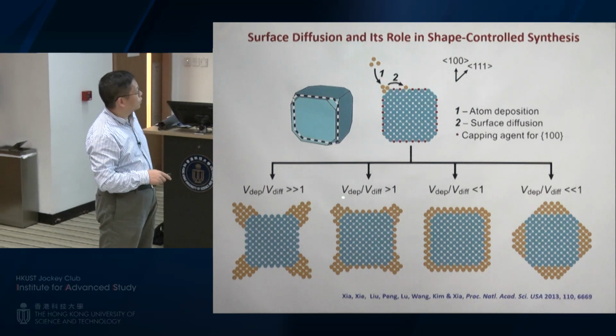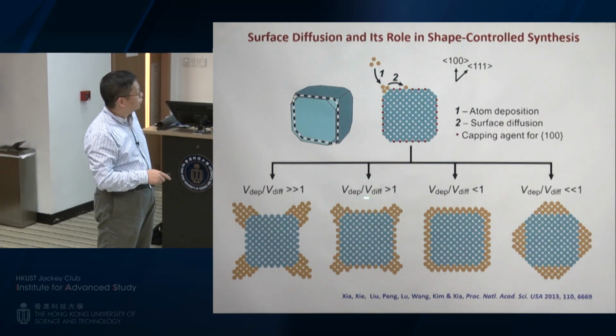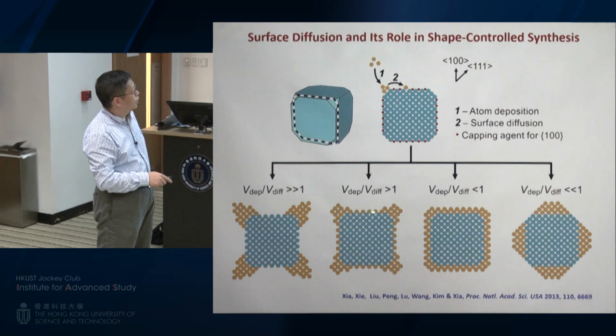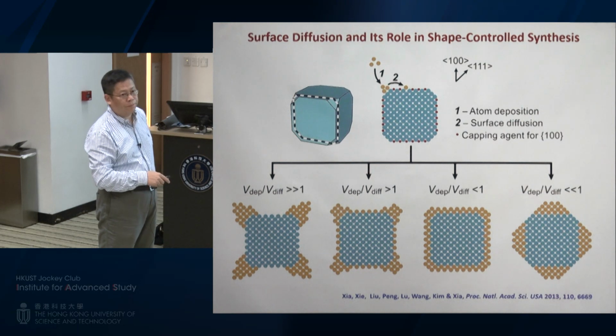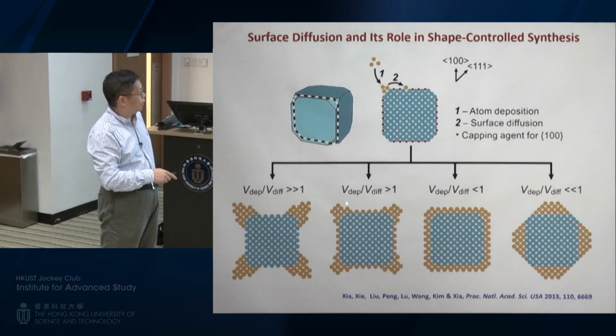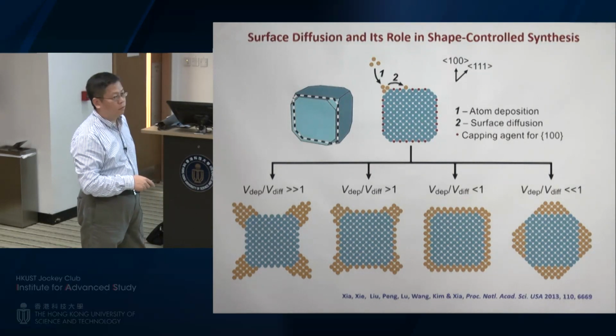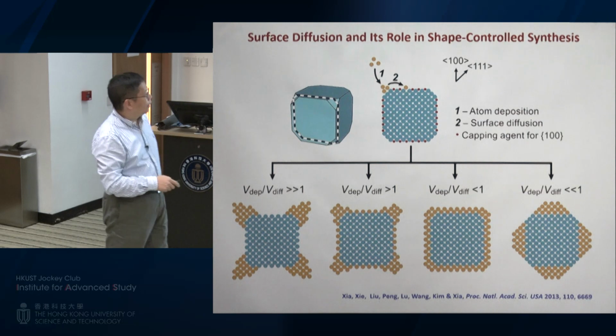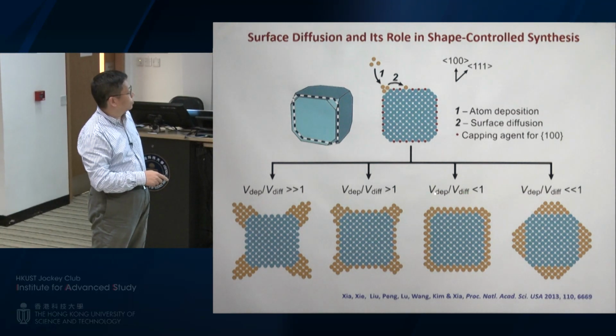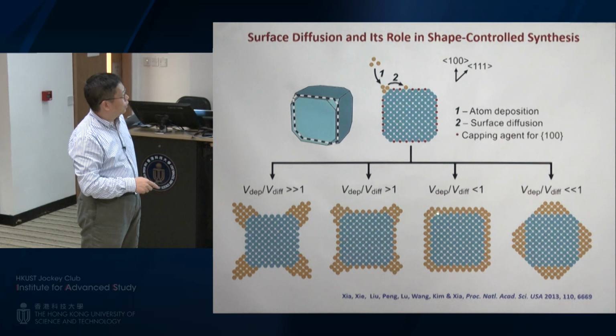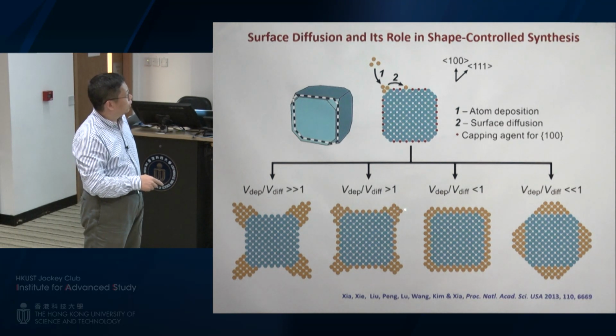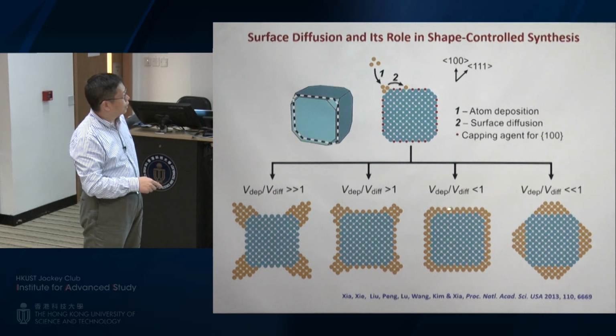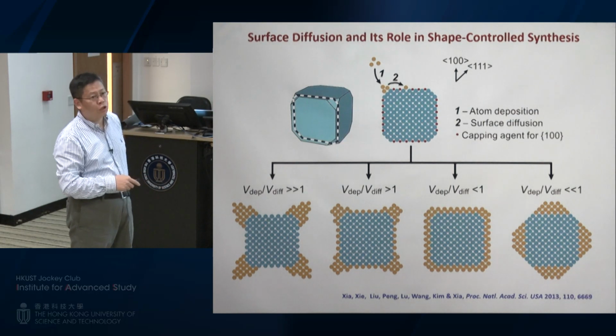And then you can have conditions with some increase of diffusion, so atoms can diffuse to the edges. What you are making here is going to be a cube frame structure. Okay, it's a cube frame. You have atoms deposited at the corner sides and the ridges or edges, and you form a cube frame structure. And then you further increase diffusion if you don't change the deposition rate. Basically, you're going to have more atoms going to edges, and at the same time even to the side faces. And in this case, you're going to form a perfect core shell structure.